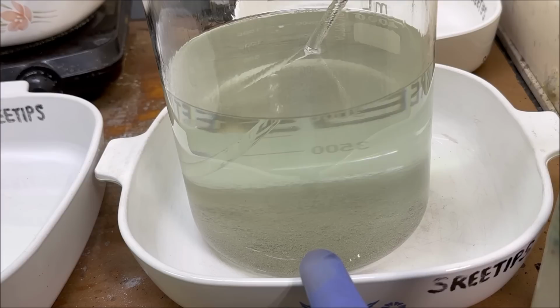Palladium is about 80 times more valuable than silver. So if we contaminate our pure silver crystal with palladium, when we go to sell the silver, we're going to be selling palladium at the price of silver. So I can tell if palladium has leached into my electrolyte, because the electrolyte will turn green.